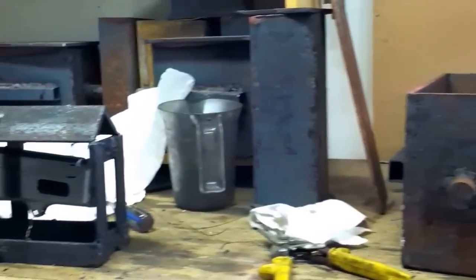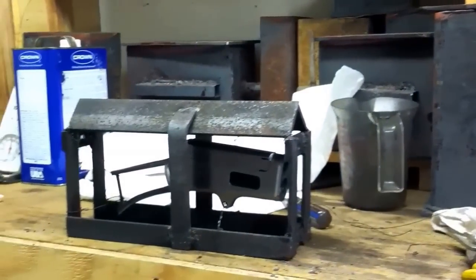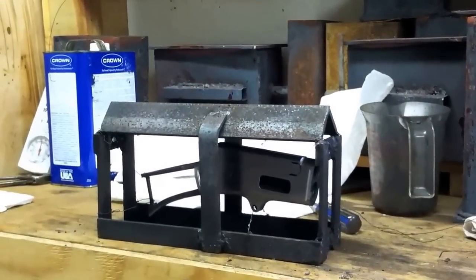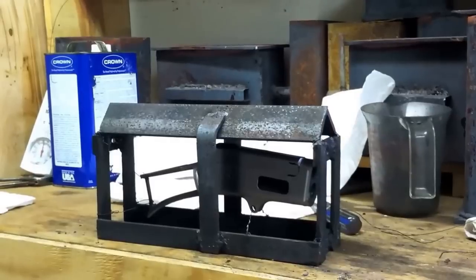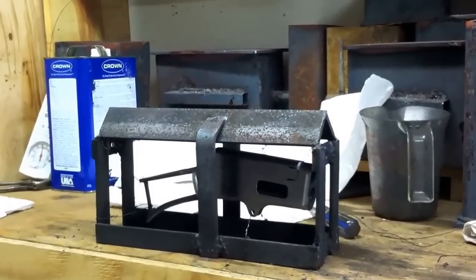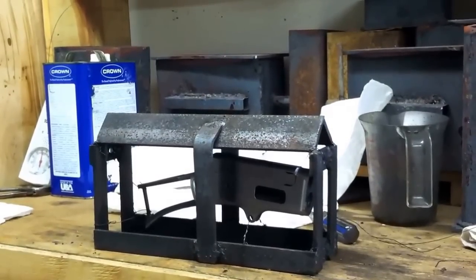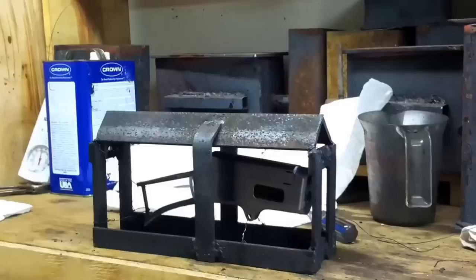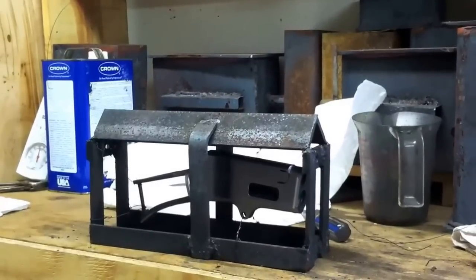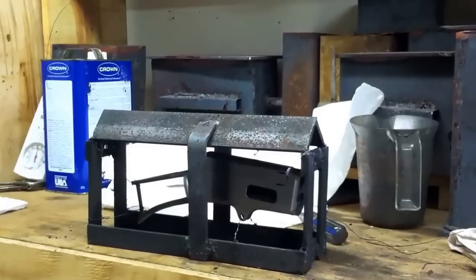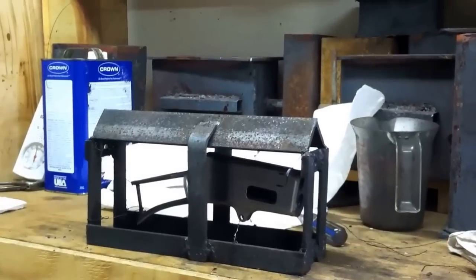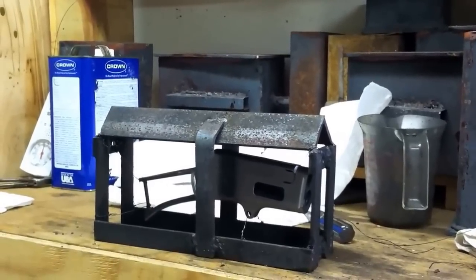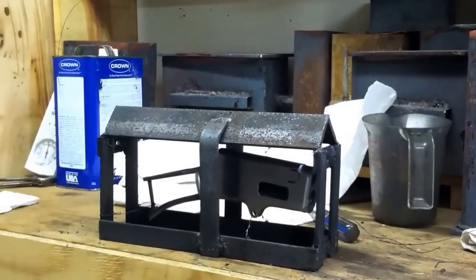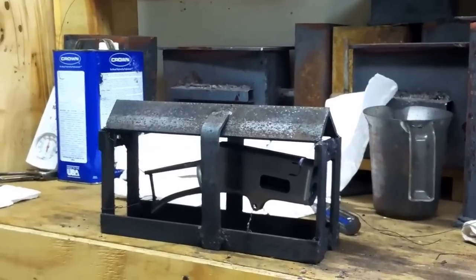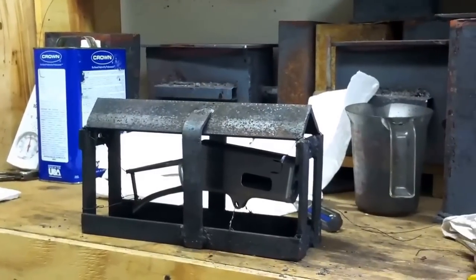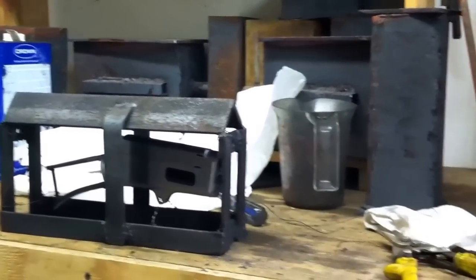The reason for the cage is, and it'll become obvious later when we get ready to quench this, we have a fixture that goes into the quench tank that the cage slides in. So when we dump the pack into the quench tank, the cage will maintain that receiver in a vertical orientation as it goes into the water and comes to rest in the bottom and cools. And we found that that is critical in getting an even color pattern on both sides of the receiver.